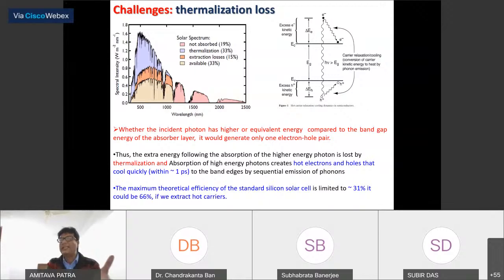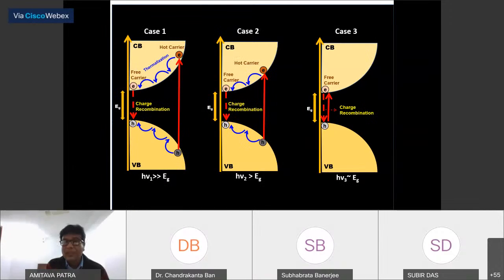This is the present thing for those who are working on energy harvesting materials for solar cells. Now what is this? On the right-hand side, in case 3, if you excite a system exactly at the band gap, where Eg is the band gap, so this is the light. If it exactly matches the band gap of your system, then the electron goes from here to there, then the electron recombines. This is the charge recombination process. Then there is no hot carrier generation. But if you excite with a higher energy than the band gap, then the electron goes from the valence to the conduction band, then there is hot carrier relaxation, and that will kill your system. That is the thermalization process. Again, if you are higher than the band gap.